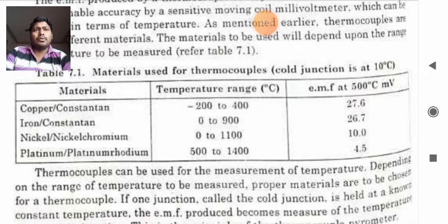Just imagine millivolts, that is not even equal to 1 volt, so very sensitive voltmeters have to be employed. For iron constantan, you will have a 0 to 900 temperature range, and the EMF generated will be 26.7. For nickel and nickel chromium, you will have 0 to 1100 degrees centigrade, and the EMF will be around 10 millivolt. For platinum and platinum rhodium, it will be 500 to 1400 degrees centigrade, and the EMF generated will be around 4.5 millivolt.